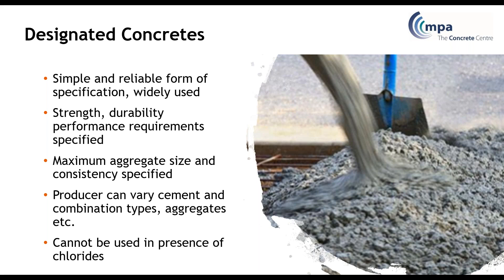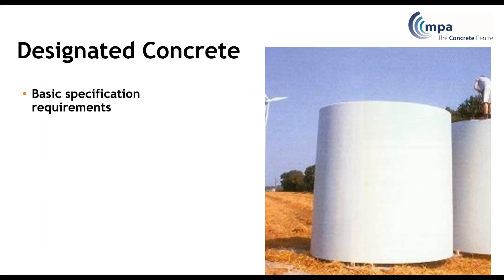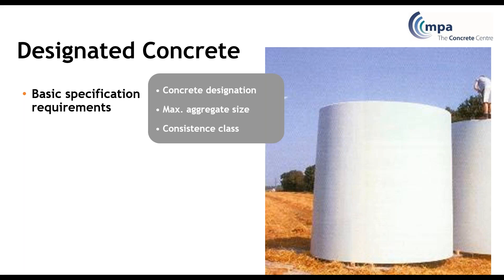The only limitation with designated concretes is that you can't use them if your exposure class is XS or XD — so they can't be used in the presence of chlorides. For the basic specification requirements of designated concrete, it's very simple: you use the concrete designation, specify the maximum aggregate size, and specify the consistency class.